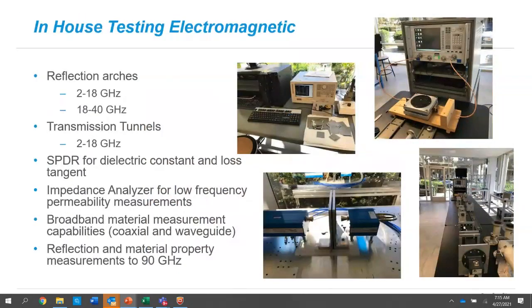And then I'm going to talk about electromagnetics because that's really the proof. You do your testing and you measure, or you take it through an environmental constraint and then you remeasure it. So certainly in the end, no matter what the environmental action is, we want to make sure the material still works. So we have a variety of ways to test low dielectric materials, low frequency materials, and up to 90 gigahertz as well. So we'll do a lot of evaluations on material, heat, humidity, and then retest for electrical performance.